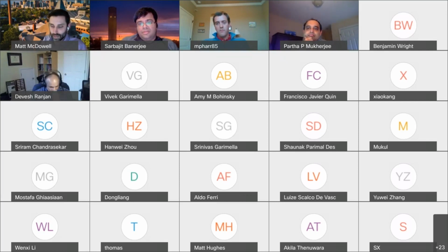In both types of batteries, you have these instabilities at interfaces. The key for the solid state batteries is that we want an interface that grows and then basically self-arrests, stops growing. To get that, you need particular properties in your interface. You need an interface that's ionically conductive but electronically insulating, so that you can't continuously shuttle electrons through to continue the reduction process. It turns out that many of these interfaces are electronically conducting, and that's when we see the continuous growth. But there are also other materials like LLZO, some other solid-state electrolyte materials that form very limited interfaces that are either kinetically passivated or even thermodynamically inhibited, arguably. So yes, it's a very critical issue, and the properties of the interface are very important.